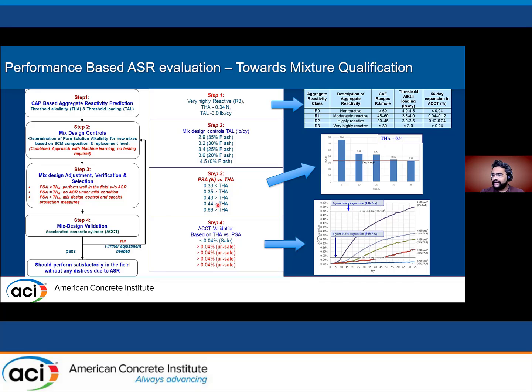And finally, it would go to the mixture validation study, probably the ACCT based test, which takes around 75 to 90 days. And we see that as soon as the pore solution alkalinity by this method was deemed over the threshold alkalinity, the expansion from the ACCT was more than 0.04%.